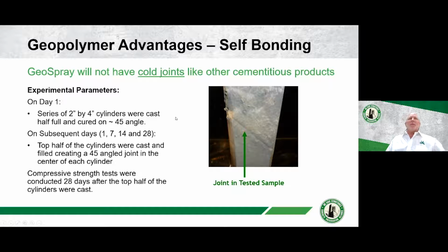Another really interesting property of the geopolymer material is that when you install it, it doesn't create any cold joints, similar to what you would get from a regular cementitious material. To prove this out, there was actually some relatively basic testing done, but I think it really shows the material well. A series of cylinders were cast. The bottom half of the cylinders were cast with a 45-degree angle on them, like you can see here in the photo. And then what was done was the top half of that cylinder was repoured, some of it 1 day later, some of it 7 days later, some of them 14 days later, and some of them even 28 days later, with no surface preparation at all on that joint.